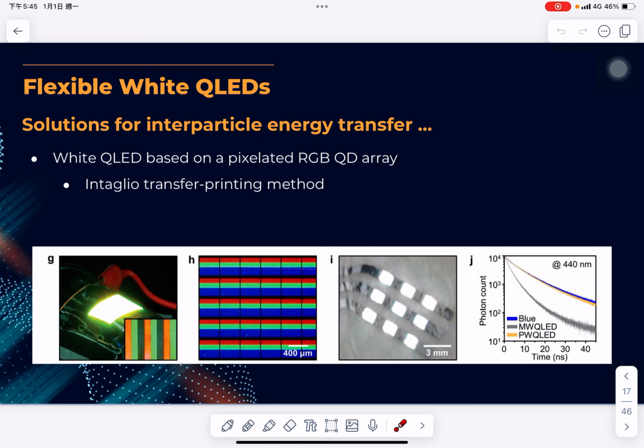The Kim group achieved a high-resolution RGB array via intaglio transfer printing. The carrier lifetime in pixelated quantum dots matched the blue layer, but was shorter in the RGB mix due to faster energy transfer. This suggests better efficiency in pixelated RGB white QLEDs. Individually controlling RGB quantum dot pixels through transistors could enhance performance at various brightness levels.